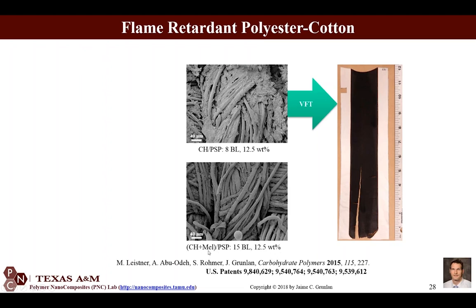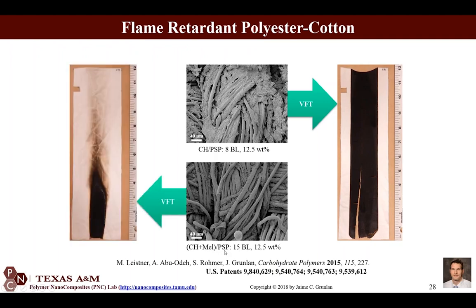Then here's 12.5 weight% of this chitosan melamine and polysodium phosphate. And that does pass the vertical flame test because of that addition of melamine, which has some kind of a cooling mechanism, and it interacts much better with the polyester. It's true also of the nylon. A recipe very similar to this can flame retard nylon. And I should mention, most of the recipes you're looking at have been further improved from what I'm showing here. So there's fewer layers to get the same result that you're looking at here.